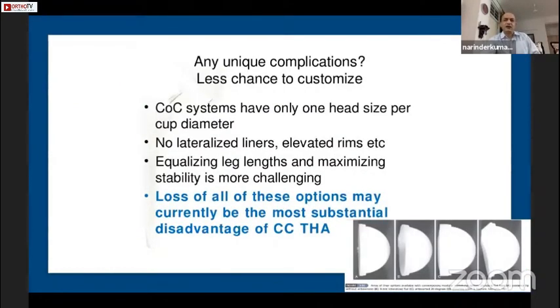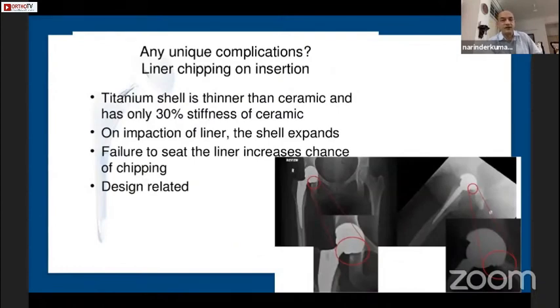And then ceramics, with their only one head size per cup diameter, no lateralized liners, no elevated rims. We have all these options in the poly. They decrease our chances to customize per-operatively. You need to have a perfect pre-op plan and go and implement it there. Because equalizing leg lengths and adjusting the offsets vertical and horizontal will become a challenge. If you are using a ceramic liner, we can't use poly for it. Even for stability also, there's no elevated liners available. So that places you at a disadvantage.